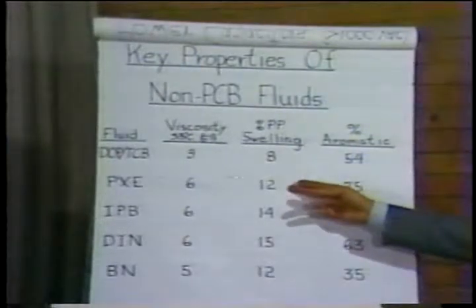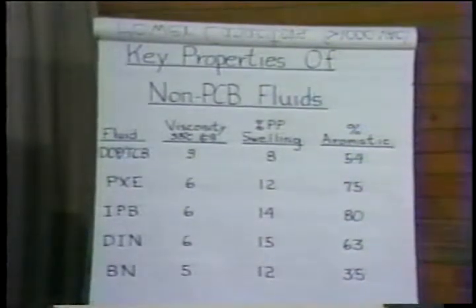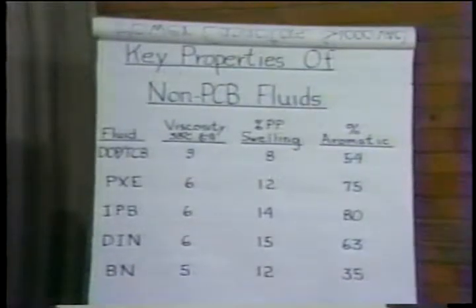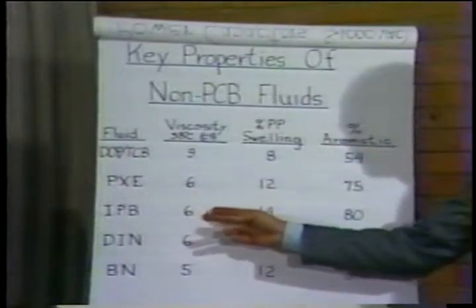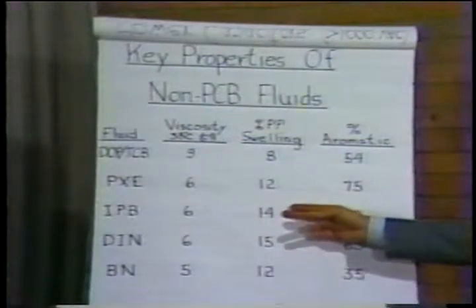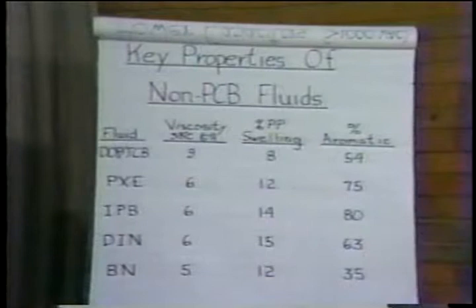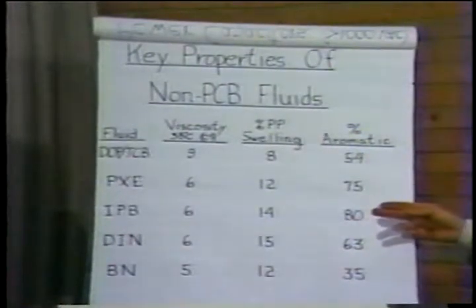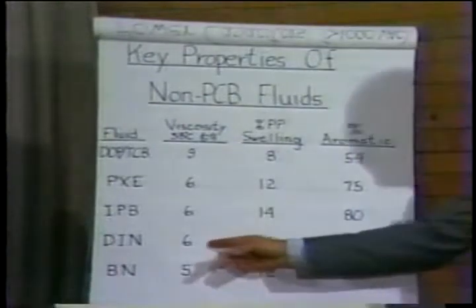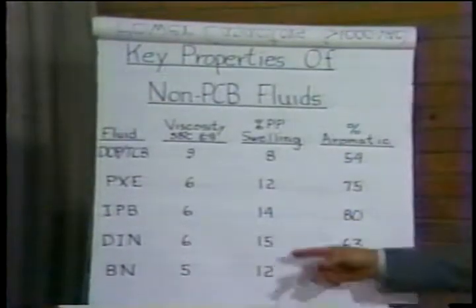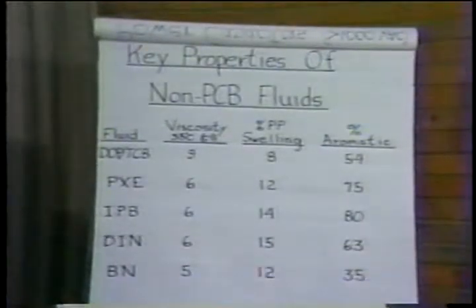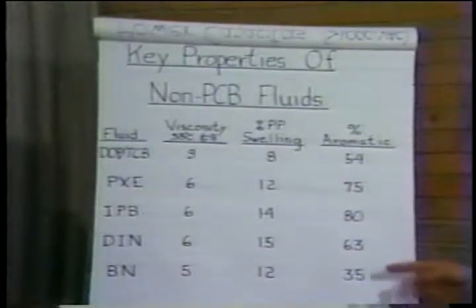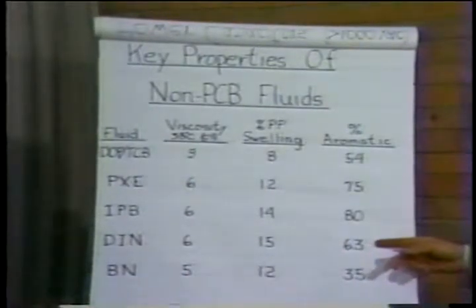PXE has an even lower viscosity. PXE is phenylxylylethane. It swells the film a little more and has very good gas absorption. Isopropyl biphenyl is another important fluid. It has a low viscosity, it has more polypropylene swelling, and very good percent aromaticity or gas absorption. Another fluid is diisopropyl naphthalene. Again, low viscosity, fairly high percent polypropylene swelling, and fairly good percent aromaticity.